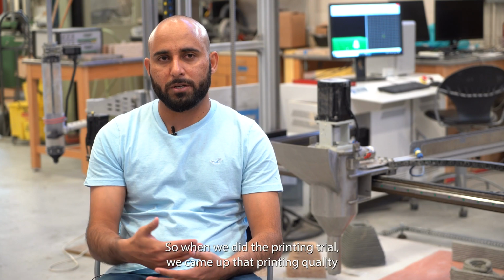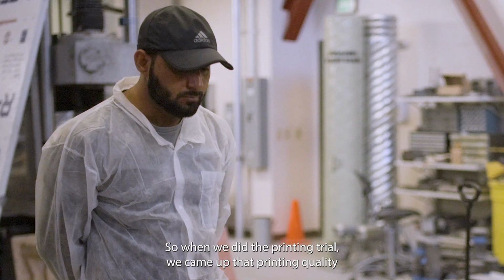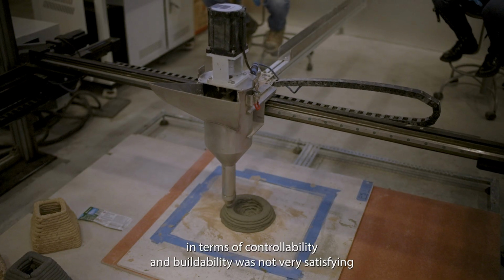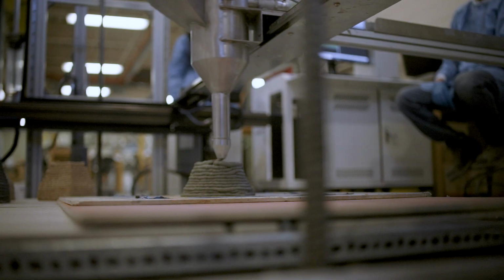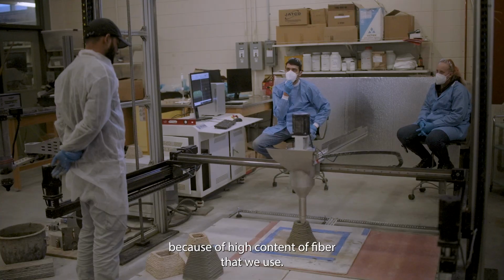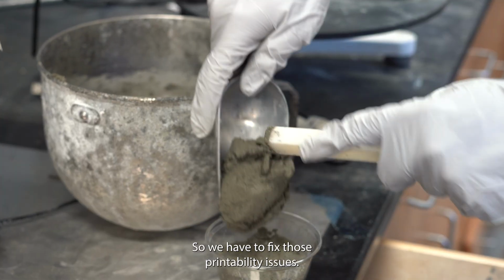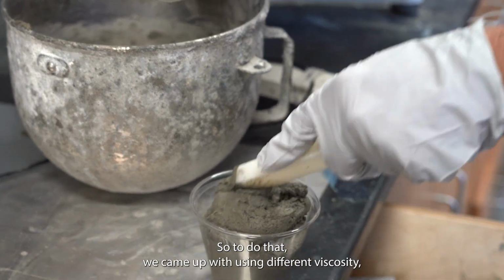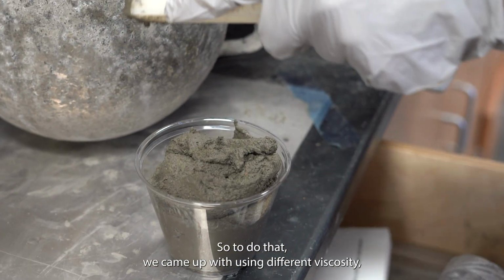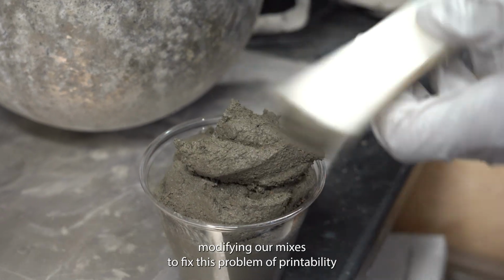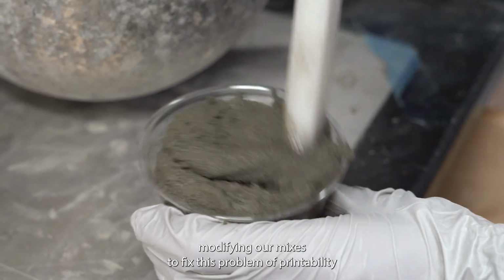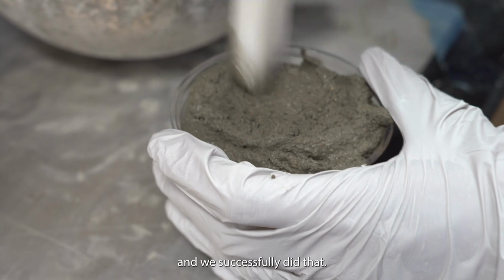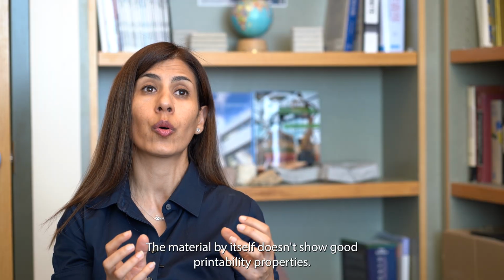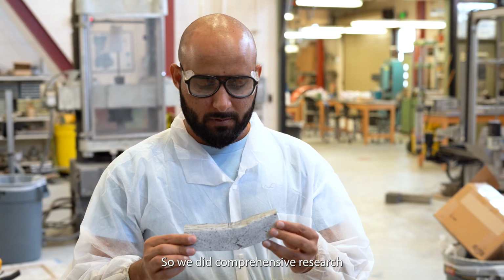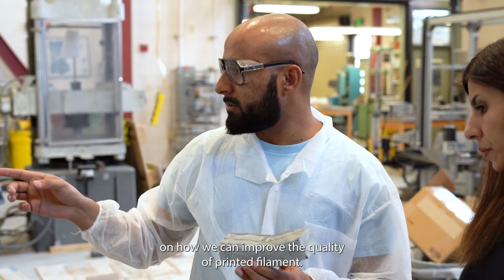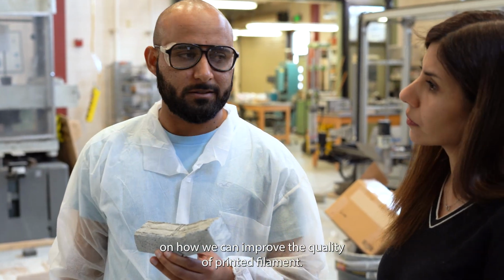When we did the printing trial, we found that the printing quality in terms of extrudability and buildability was not very satisfying because of the high content of fiber that we use. So we had to fix those printability issues. To do that, we used different viscosity modifying admixtures to fix this problem, and we successfully did that. The material by itself doesn't show good printability properties, so we did comprehensive research on how we can improve the quality of the printed filament.